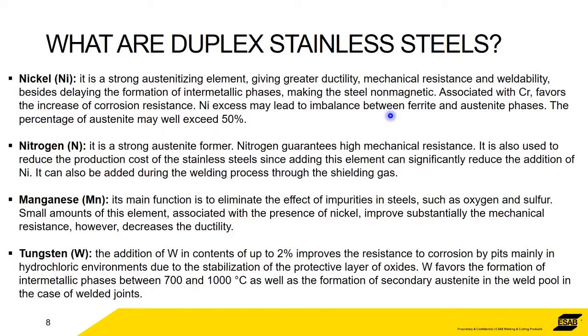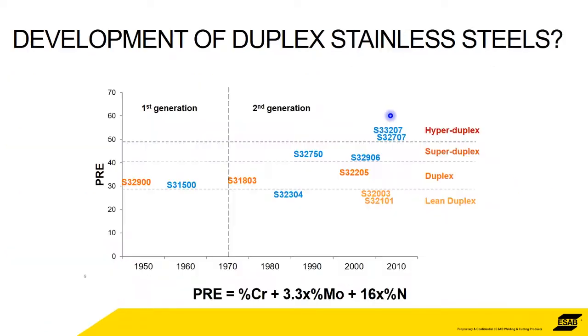Manganese is good for getting rid of impurities, as with any steel. Small amounts of oxygen and sulfur within the impurities, that manganese will eliminate the effect of those. Also some manufacturers use tungsten up to 2% to improve the corrosion resistance. The addition of tungsten does make a less stable alloy than those without. So there are grades of super duplexes that use tungsten, and there are grades that are also super duplexes, but they have no tungsten in them.